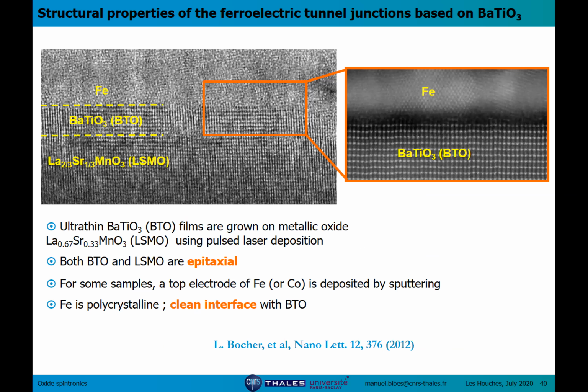So here I'm showing some TEM image of devices we made to study this effect. We use LSMO as our bottom electrode. It's magnetic, but let's forget about its magnetic properties for now. And barium titanate, which was our ferroelectric, and everything was grown onto neodymium gallate, which imposes a large strain on barium titanate and enhances its ferroelectric behavior, especially at low thickness.